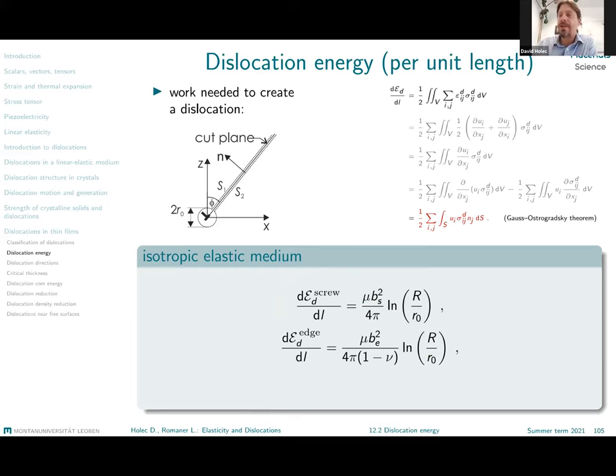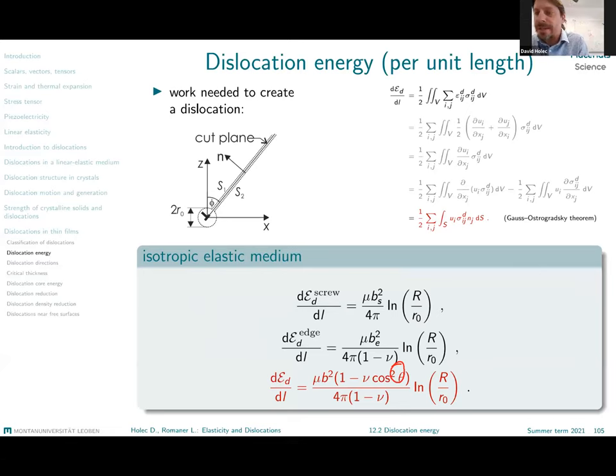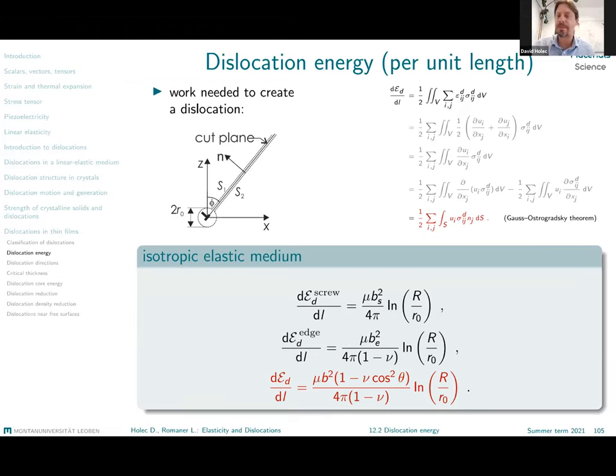When we have a general dislocation in the elastic medium, we simply combine those two formulae, where the angle theta plays a significant role — it corresponds to the angle between the dislocation line and the Burgers vector. So for theta equals 90 degrees, we get edge dislocation. Eventually this formula is the central formula for the majority of the evaluations we'll be doing here today.